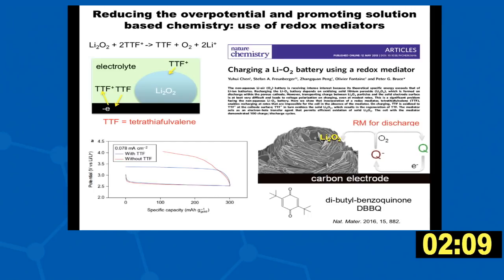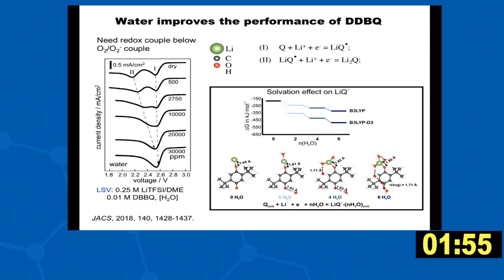The difference now is that the quinone itself gets reduced. It then finds, on the carbon electrode, an oxygen molecule, and then it can react anywhere to form these extremely large lithium peroxide particles. And so what we've been doing is to work on the effect of water and these DBBQ molecules.